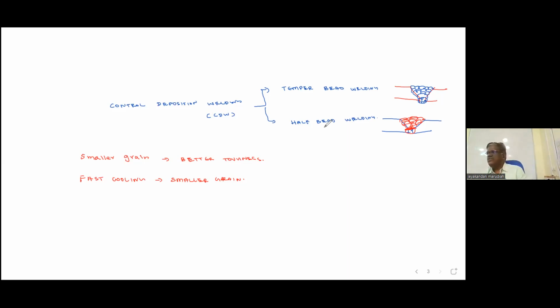So what is meant by procedure qualification? Take the same tank material, make a PQR by using temper bead welding or half bead welding, then send it for impact test. If it passes the impact test, it means the toughness is improved by welding. That's all. Okay, this is called temper bead and half bead welding.